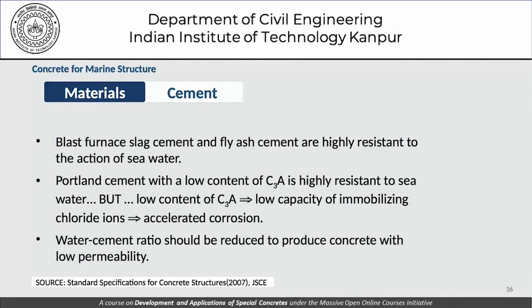Blast furnace slag cement and fly ash cements are highly resistant to the action of seawater. Portland cement with a lower C3A content is highly resistant to seawater, but with low C3A it has a lower capacity for immobilizing chloride ions, which can have implications for corrosion. The water cement ratio should be reduced to produce concrete with low permeability.